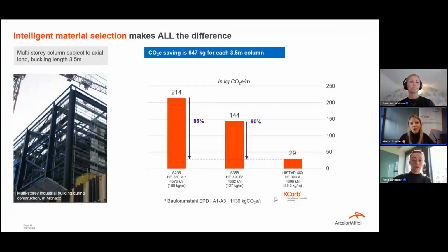Talking here, for example, about the columns, it's a simple but quite straightforward and clear example. We consider a steel column subject to axial loading, buckling length 3.5 meters. We make a first pre-design, and we see that if we make our design in S235, so very basic steel grade, we would require as section an HEM 280, which is almost 200 kilos of steel per meter. But then we just change the steel grade and we go for S355, which is also quite basic actually, but which is better than S235. Now the required section is smaller. It's an HEB 320. So we're reducing the weight of the column. We're making savings in terms of carbon. And then in the third case, we're actually accumulating two things: the use of HISTAR 460, so an even better steel grade, and xcarb. Combining these two, the reduction is even bigger.